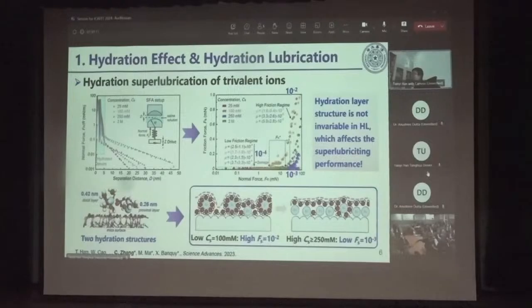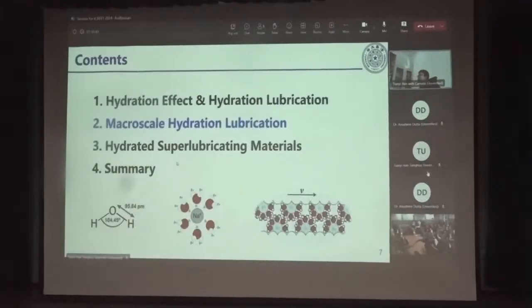So these works by Professor Klein's group and our group suggest that maybe we can get super low friction by the hydration effect for macroscale contact, because all this previous research used an SFA setup. The contact is very small, so we call it a microscale contact. So how can we use this hydration lubrication at a macroscale contact? Then I will introduce how we get superlubricity at a macroscale contact based on hydration lubrication.